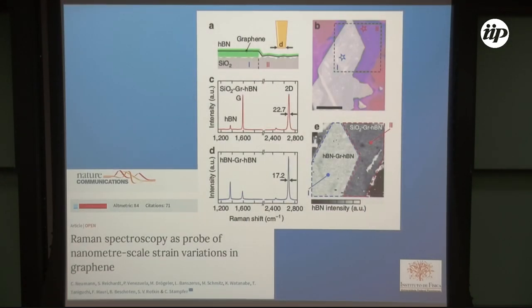Okay. Another example of application of our methodology. This is a very nice experimental work done basically by Christopher Neumann in the Christoph Stampfer group, also from Germany. They did several beautiful experimental results. I don't have time to give all the details of the work. I just give you a glance of my theoretical participation. So basically, they have this amorphous substrate, and here they put boron nitride in one part of the substrate, and above that they put graphene. So graphene in part one is on a very flat substrate, which is boron nitride, and here it is on a very rough substrate, which is amorphous silica.